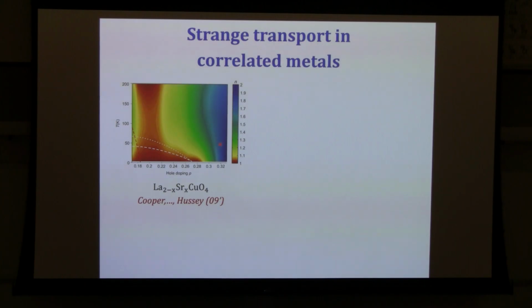And what you see again is this color plot, the exponent of the resistivity, where 2 is what we would expect for a Fermi liquid. And you see this very strong deviation from 2. It's actually close to 1, close to linear in T resistivity. This is the famous linear in T resistivity in cuprates. But unlike the cases shown before, this behavior is not confined to a quantum critical point. It actually extends over a whole regime of doping.